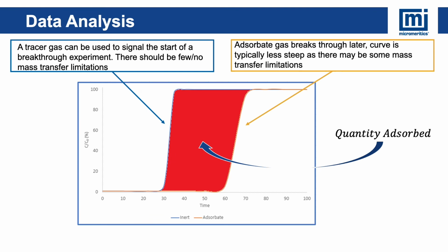Looking at what this would look like in terms of the breakthrough curve, we can see that we have essentially two breakthrough curves here. We have our inert gas, which breaks through immediately at the start of our experiment, when we first open those blending valves, say that happened at time equals 30. We also see a very steep breakthrough curve, because if we're using something like helium, which is very small, we don't expect there to be much mass transfer limitations, so we'll get a very steep breakthrough curve. Our adsorbate gas breaks through later as our sample column adsorbs that adsorbate. And then also, it's pretty typical to see some amount of mass transfer limitations, so you might have a little bit less steep curve. The total quantity of gas adsorbed will be the area between these two curves, which is highlighted in red.